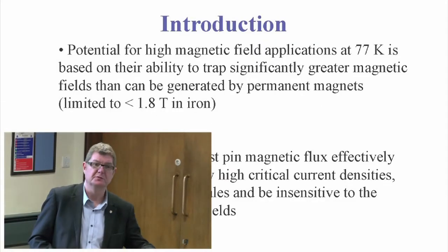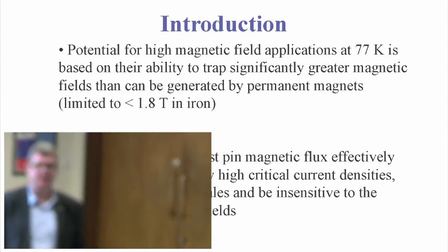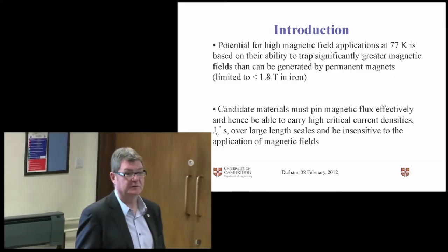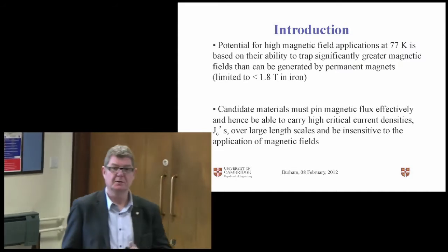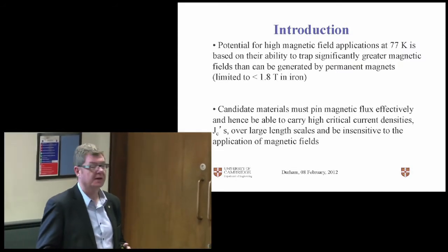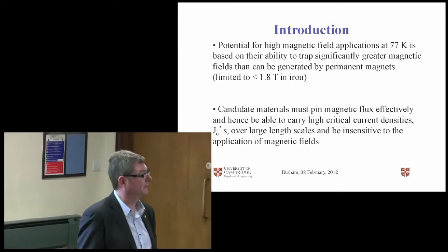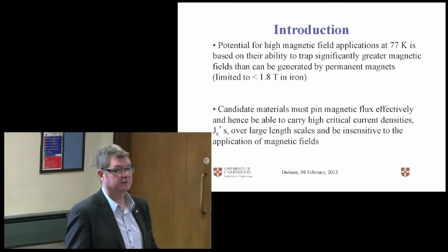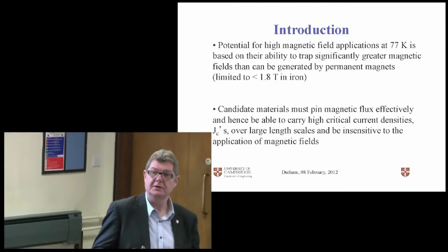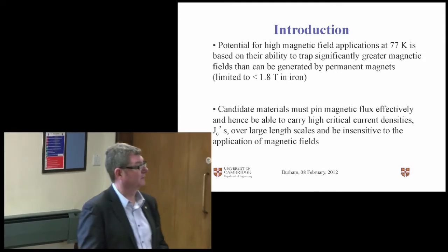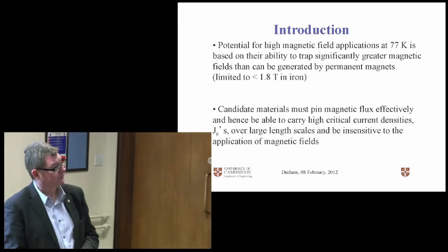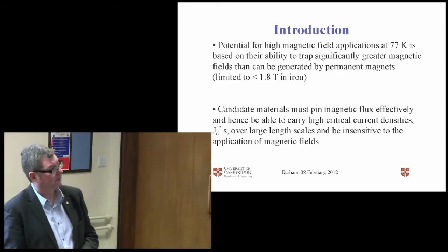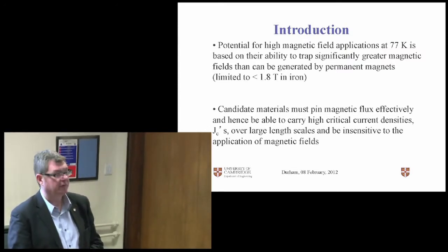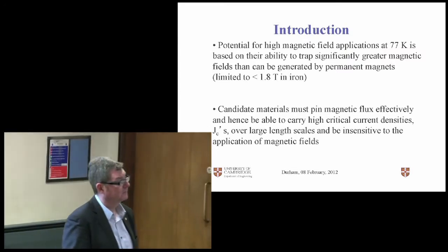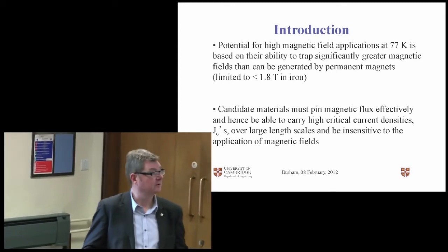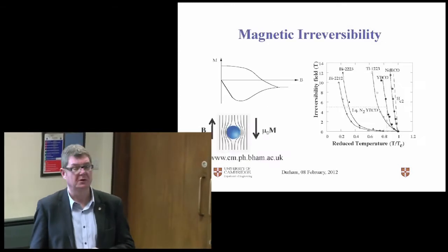And these lines can move through the superconductor, which gives a dΦ/dt, and therefore an EMF, and therefore dissipation when current flows. So if you can stop those flux lines moving, you get no induced EMF, therefore no loss. So you get lossless current flow. So the challenge is to put obstacles in the way of these flux lines and stop them moving, and that's flux pinning. So if you can do that, and you can generate large currents over a large length scale, and you can make the whole thing insensitive to the application of a magnetic field, then you have a material that potentially can generate a large current, and a large current means a large magnetic field.